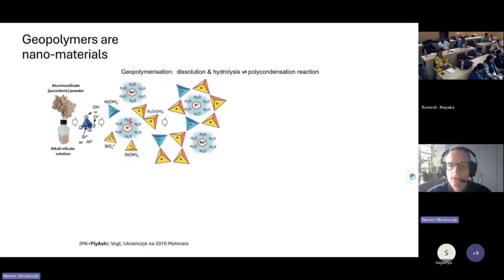So you have aluminosilicates. Here you don't have calcium, basically, and this is what makes it acid resistant. You have these aluminate tetrahedra and silicate tetrahedra, which you have with aluminosilicates like, for example, clay minerals, and they are dissolving. You have potassium activators, hydroxide activators, and silicates, which then polymerize. Those are the tetrahedra, aluminates and silicates. Silicate is neutral, this is the silicate tetrahedron, and aluminate has one negative charge. And basically you are just linking those tetrahedra. It's called polycondensation, because you are basically releasing water. Those are the oxo bridges in between.